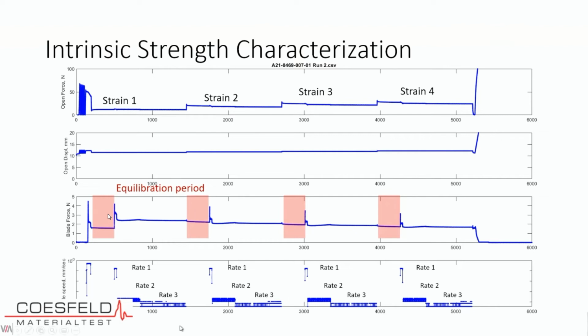At each strain level, we go through a schedule of different cutting rates. So you can see on the bottom plot, I'm plotting the rate at which the blade is progressing as a function of time. During the period of strain 1, first I go through an equilibration. So this pink region here, right? I stretch the specimen, I put it at strain 1, and then I hold there for 5 or 10 minutes, depending on how you set up your test. And the point of this is before you do the cutting motion, you want the rubber to be in equilibrium. We're trying to get rid of any viscoelastic dissipation that could happen in the rubber. So you want to give it time to equilibrate. And then once it's equilibrated, we begin pushing the blade into the rubber at a series of controlled rates.